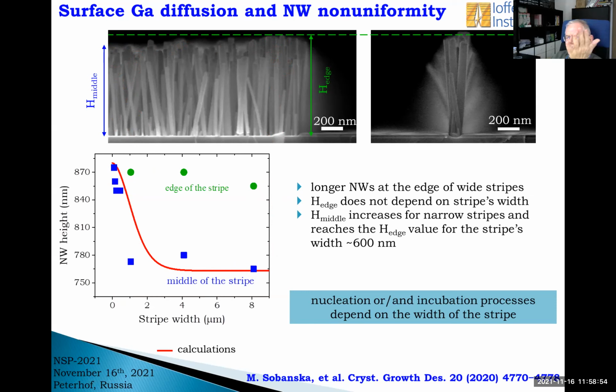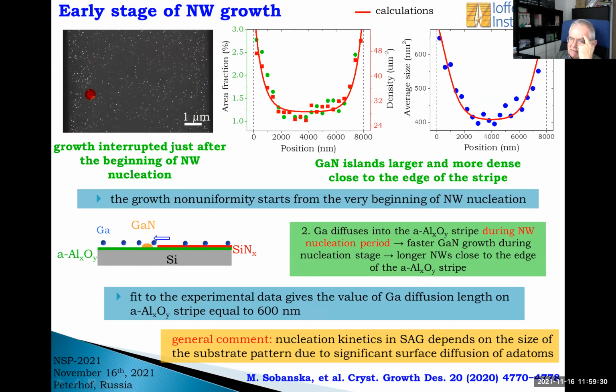In order to answer this question, we have considered various scenarios, but this experiment gave us a final answer. This is growth interrupted at the very beginning of nucleation. So when the first nuclei appeared on the surface, and then we studied distribution of these islands across the stripe, meaning their size and density. And here you have a plot showing that here close to the edge, these islands are larger and more dense than in the middle. So this tells us that growth nonuniformity starts from the very beginning of nanowire nucleation.